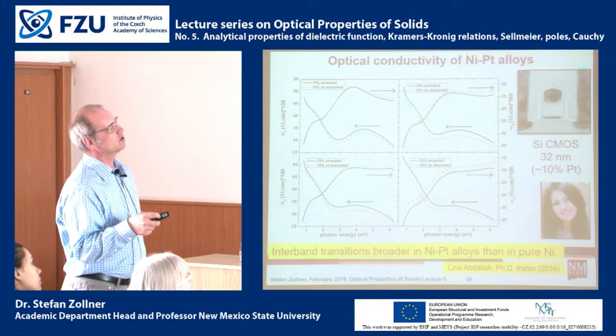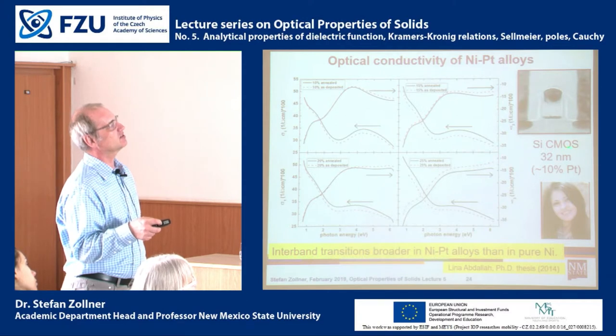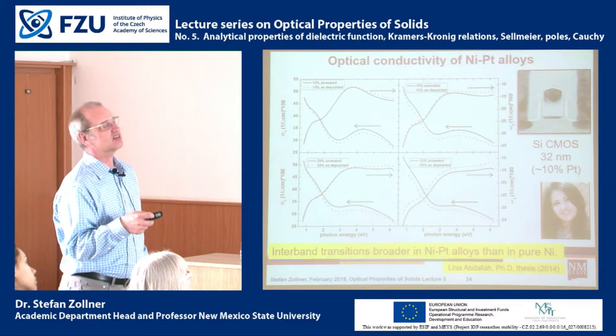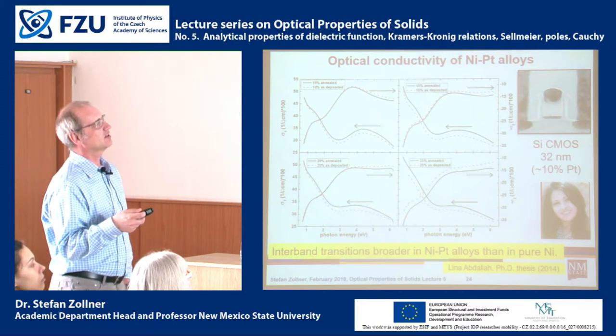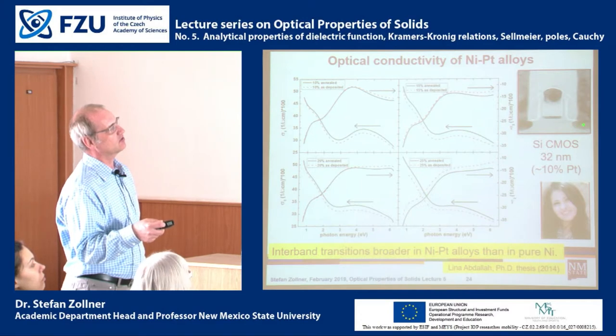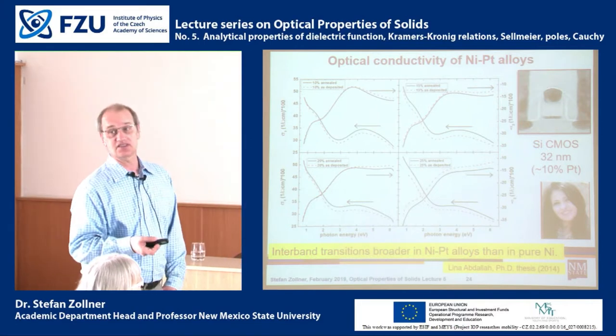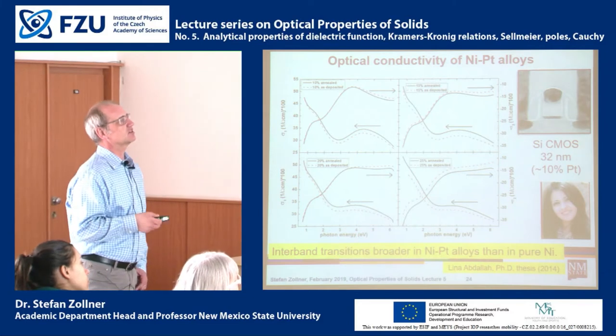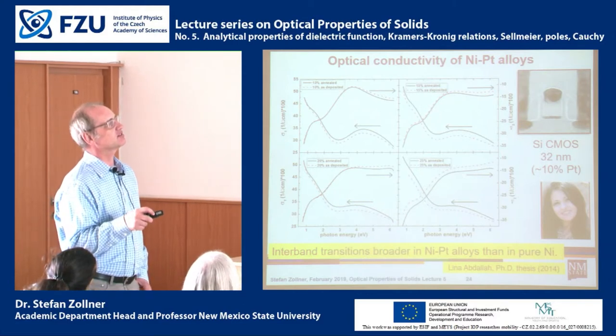So this shows a picture of a silicon CMOS field effect transistor with a 32 nanometer gate width, and this dark area is a transmission electron micrograph. The dark area shows that you have a metal, and the contacts to the source drain regions, so this part and this part, those are the contacts to the source drain region, as well as the contacts to the polysilicon gate. They're all made with nickel silicide, and that's why we were interested in the optical constants of nickel, to see whether one can measure the nickel thickness or the nickel silicide thickness using optical methods.